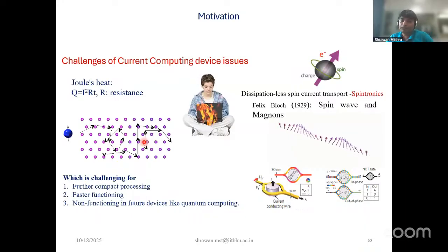And transportation of the spin wave, or magnon-based devices, don't require any electrical bus to pass the current, so they hardly generate any heat component. That's a transfer of spin from one side to another, which is possible throughout the lattice. But the challenge is that this spin wave cannot propagate for a longer distance. For electron transportation, if you have a continuous circuit, no matter whether it's a kilometer or a millimeter, it will travel without much problem. Maybe some scattering and resistance, some decay will occur. But a spin wave is very difficult to propagate more than a micrometer. So it will dissipate within the range of a micrometer. That's the biggest challenge.